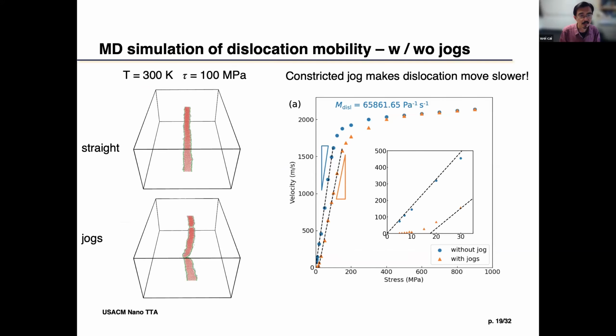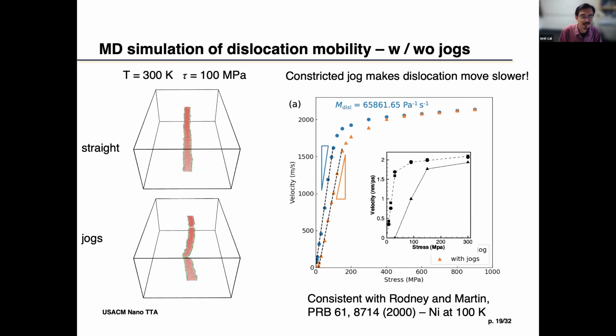So I think that confirms that indeed jogs are happening. First of all, jogs are happening when you're in a multi-slip orientation, but then when they appear, they can severely lower the mobility of dislocations. After we did that, we realized that there was actually a study earlier, in the year 2000, by David Rodney. We happened to use the same potential, and they did the study at 100 Kelvin and reported very similar findings.